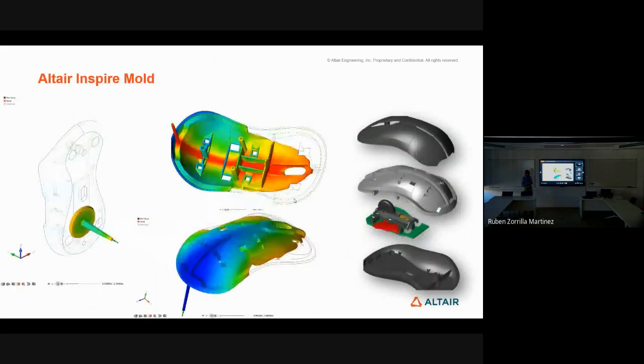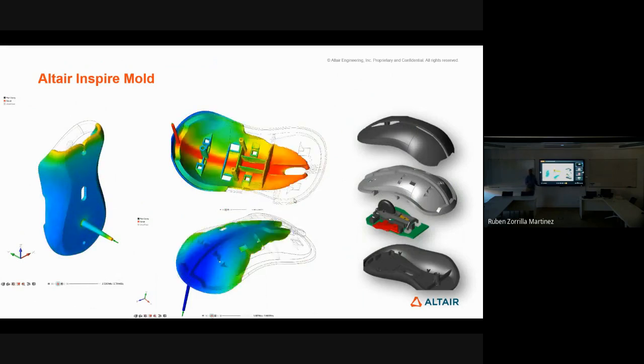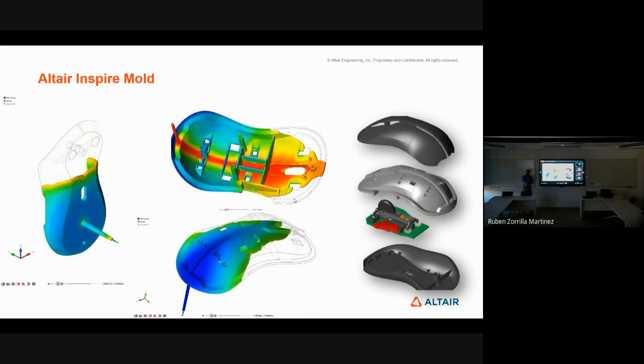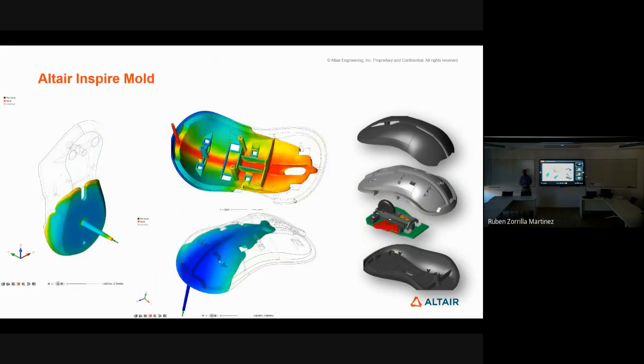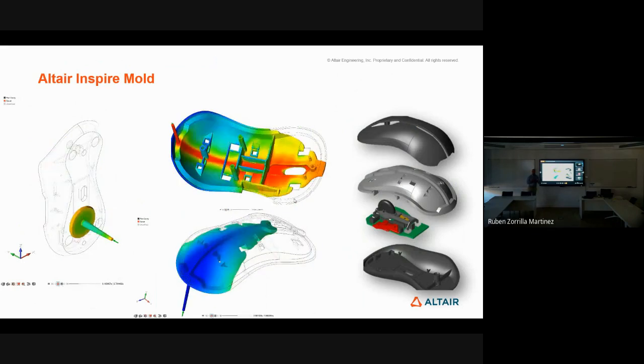Then we have the molding one. This was by far the most complicated solver that I have written in my life. It is one of the very few cases that I know where the thermomechanical problem is two-way, not one-way. So it's not that you calculate the temperature and then go for the fluid, calculating the Stokes. The fluid is Stokes, so it's not very difficult. What is problematic is the shear heating, which means that the energy released by the strain of the polymer gives a lot of temperature. And polymer is very temperature resistant, the diffusivity is very low, it's not a good conductor. This makes it very, very tough. In fact, if you don't take into account that strong coupling, it doesn't work. Basically, it will say that you cannot fill. It's a very tough solver, this one.